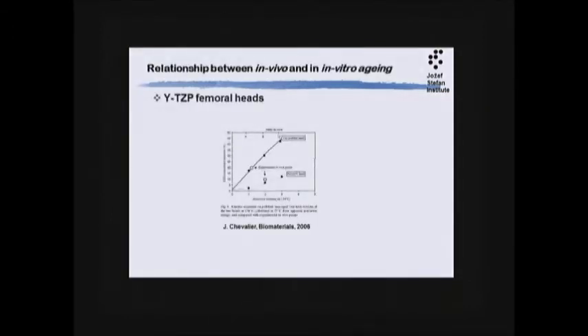Okay, and that's the well-known relationship between the in vivo and in vitro orthopedic zirconia femoral heads. But one has to be aware that this material was hot isostatically pressed and mirror polished. So the material is fine grained, it behaves differently, and also the surface is polished, in contrast to a rough surface as you have in a dental lab.